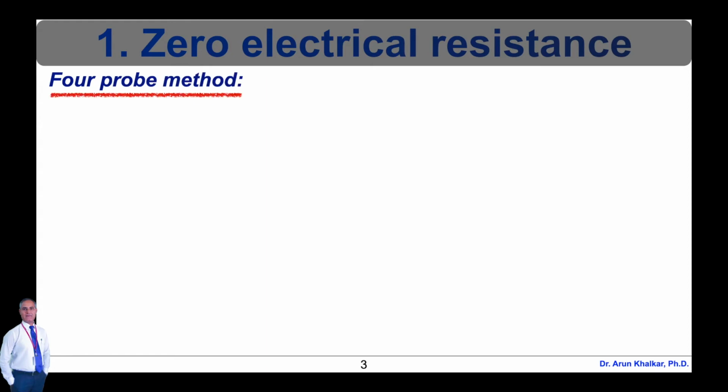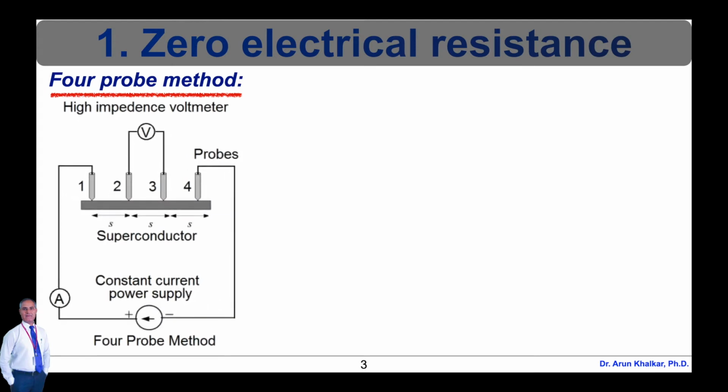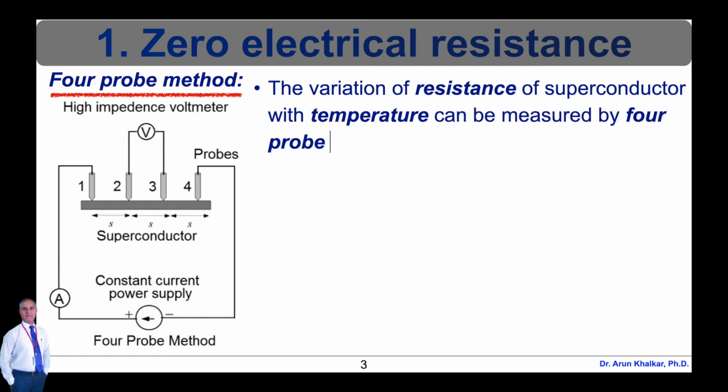The most obvious characteristic of a superconductor is the complete disappearance of its electrical resistance below a temperature that is known as its critical temperature. Experiments have been carried out to detect whether there is any small residual resistance in the superconducting state. A sensitive test is to start a current flowing around a superconducting ring and observe whether the current decays. The current flowing in the superconducting loop clearly cannot be measured by inserting an ammeter into the loop, since this would introduce a resistance and the current would rapidly decay.